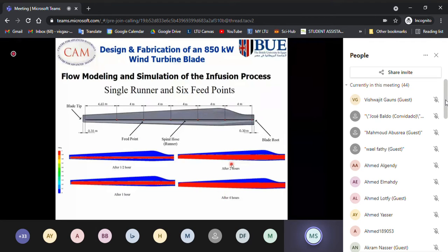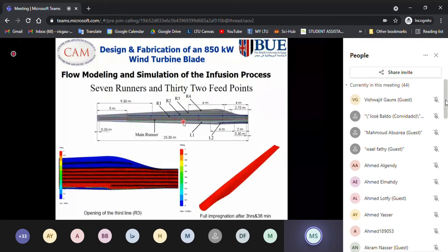So we went through different trials, and the last one that we adopted was 7 feeding lines and 32 feeding points. As you can see, the full impregnation of the blade occurred in 3 hours and 38 minutes.